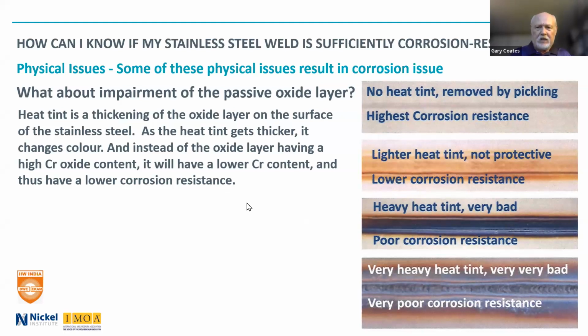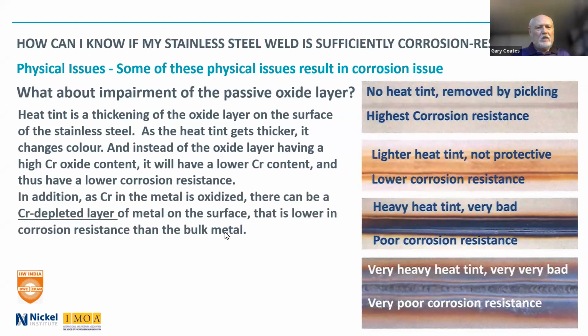And on the right, you can see some pictures. The one is of a weld. The one at the top, the heat tint was removed by pickling, no heat tint. Lighter heat tint, heavy heat tint, which is very bad. And then the very, very heavy heat tint is very, very, very bad.